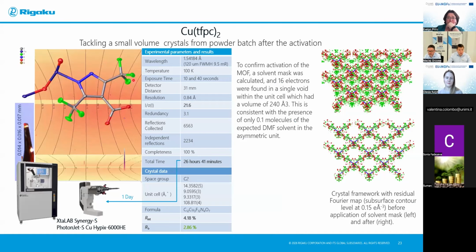So as an example, say we still have a powder batch. Here is one of Maciej's MOFs that Maciej measured. He actually activated the MOF, so he heated it for an extended period to get rid of all the solvent from inside, which very often results in the single crystals no longer being single crystals, or being very small. You can see the size of the crystal on the mount: all dimensions are less than 20 microns. The measurement on modern instruments takes a day, unless you have a Rigaku high brilliancy rotating anode source, then it's a factor of 10 faster, so basically 2 hours.